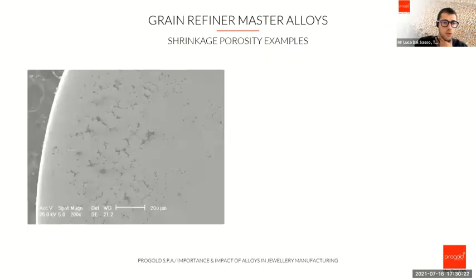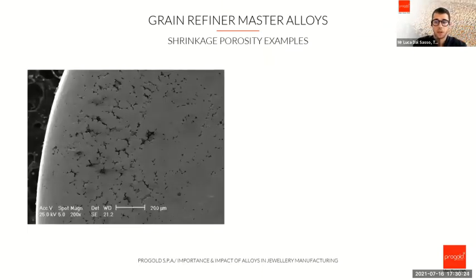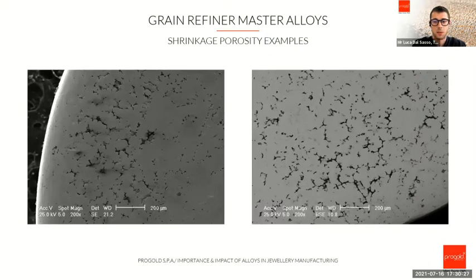Going on, we have another very famous and very common problem for jewelry producers, which is the shrinkage porosity. What is the shrinkage porosity? When the metal inside the mold starts cooling down, so during the cooling phase, it is in contact with the walls of the mold, and the metal going from the liquid state to the solid state starts to shrink a little, because it's a feature of the metal.